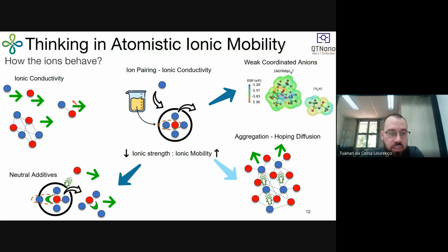So the total charge here is zero, so this is not good for ionic conductivity. Also, we have this kind of structure in which we have some aggregation, and so we can see the motif moving together, and also here, zero charge because we have 3 positive, 3 negative. However, sometimes we can see an extra anion here, so we have unbalanced charge, and this is good for ionic conductivity. Also, we need to correlate ionic conductivity with the structure.